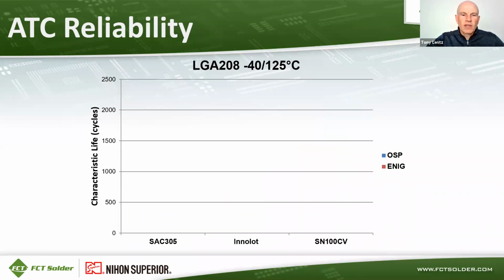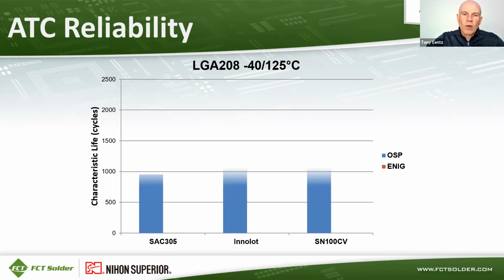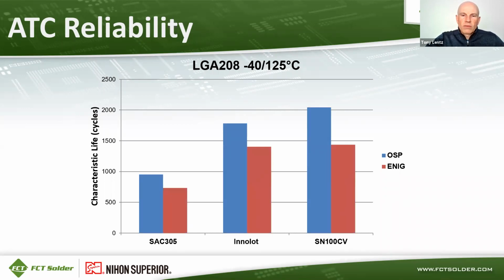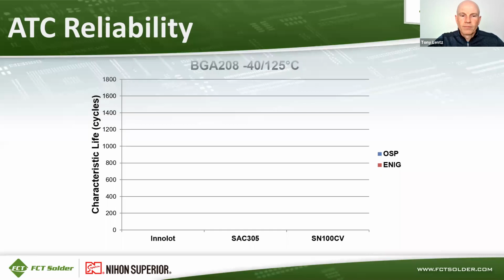And then here's the data for the LGA 208 with three of the alloys, SAC 305, Innolot, and SN100CV. So the OSP data shows SAC 305 has the lowest life, Innolot was in the middle, and SN100CV actually was the best performing alloy on OSP. And on ENIG, SAC 305 again had the lowest life, and Innolot and SN100CV were tied for the lifespan that they lasted for this LGA 208 component.